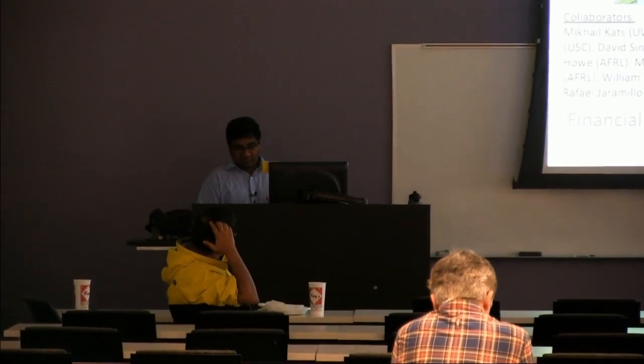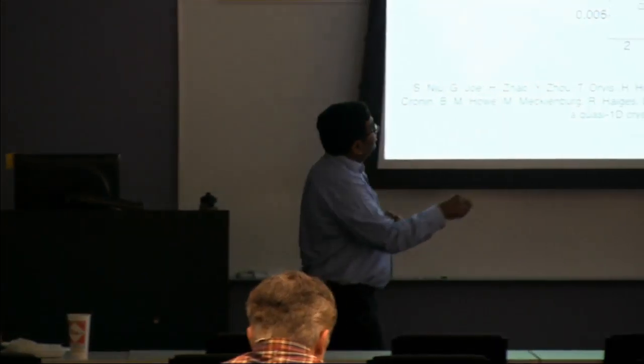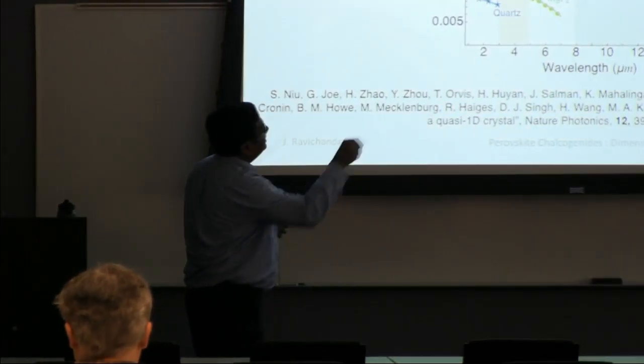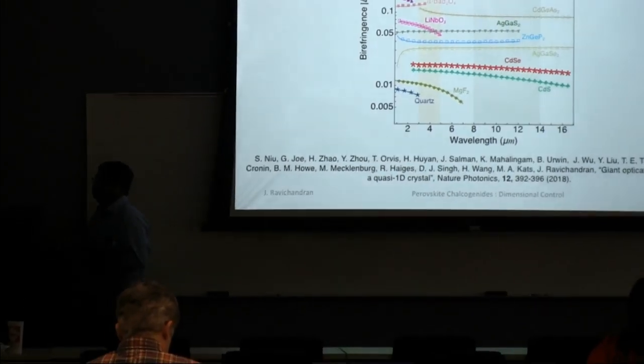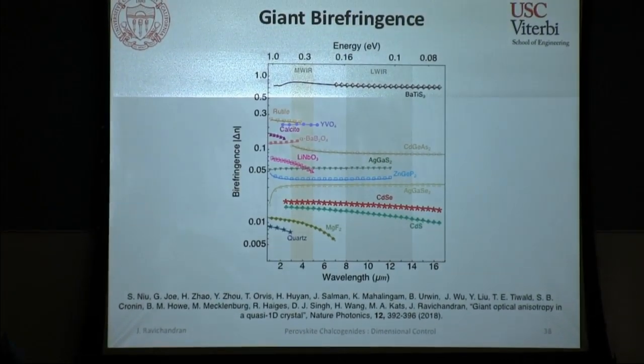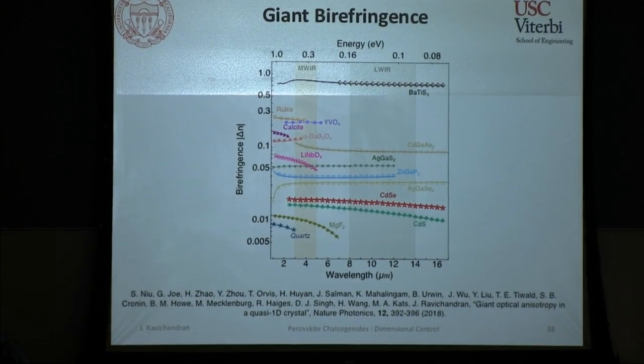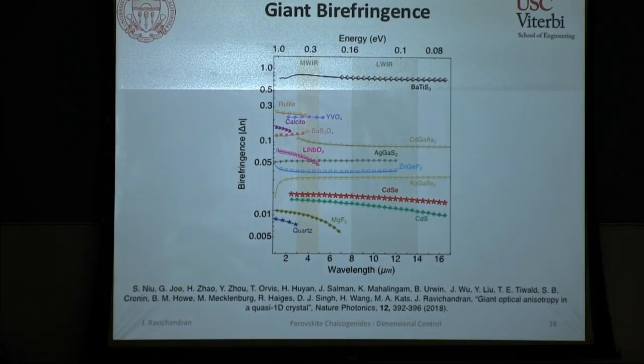Yeah, so that's a very important question. So growing large single crystals in sulfides, for example, if you look at the graph that I showed, there's a lot of effort in growing these chalcopyrite type, pnictide and other sulfide type materials. And most of the times people are using Bridgman type method to grow it. You can also use traveling heater methods. There are different ways where you can make it larger. Right now we are using vapor transport. It's not a scalable technique. You can get a few millimeter size crystals if you're lucky. But Bridgman is the way to go to make larger crystals.